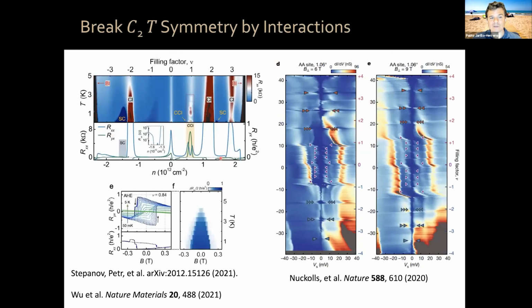Now, more recently, people have realized that the C2T symmetry can be broken without hBN alignment and at zero magnetic field. Just interactions themselves can spontaneously break C2T symmetry and lead to this type of topological physics that I'm mentioning, okay? So for example, the group of Dima Efetov at ICFO has shown that you have these strongly anomalous, not quite quantized, but very high anomalous Hall effect, in structures which are not in principle aligned to hexagonal boron nitride, and they can see this anomalous Hall effect at zero field. Okay, the group of Ali Yazdani has also shown in a very interesting experiment, STM experiments, how interactions can break spontaneously that C2T symmetry.